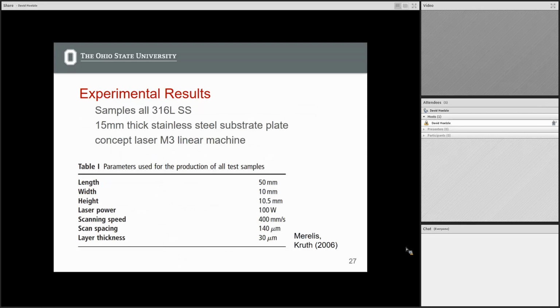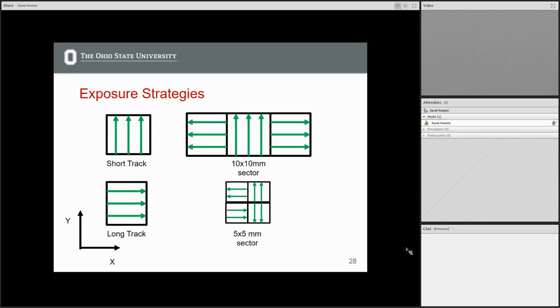So their experiment was still with 316L stainless steel, so that way they could compare it to their theoretical results. And they were printing using a rectangular shaped component. The length was 50 millimeters and the width was 10 millimeters. And that's going to be important for their scanning strategy, which can be shown here.